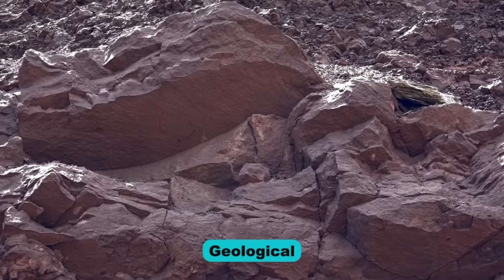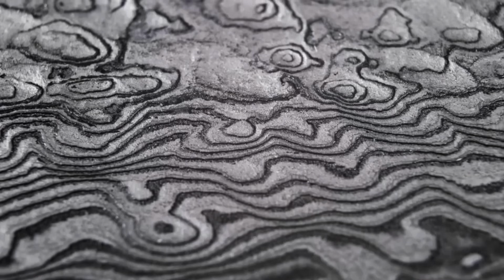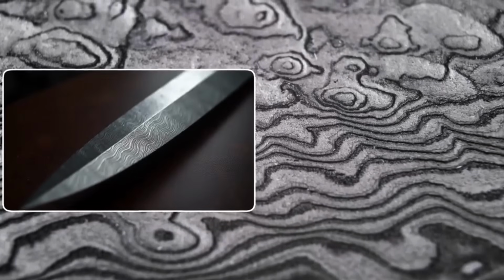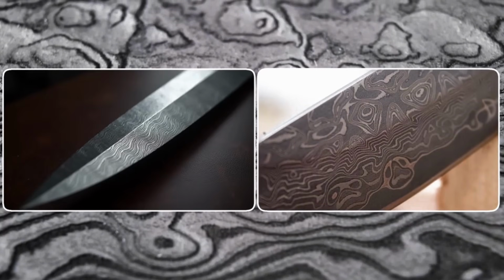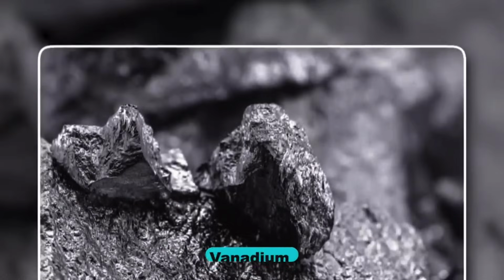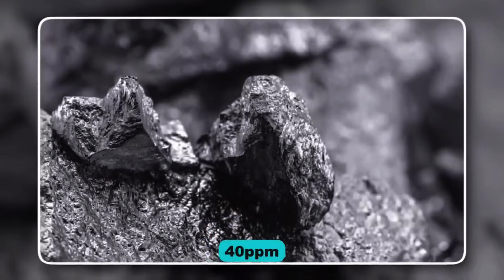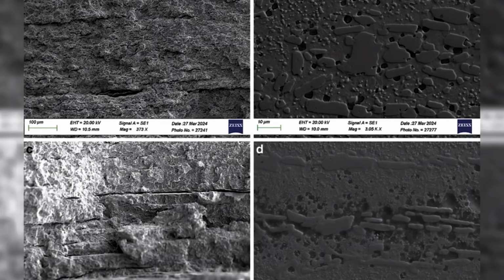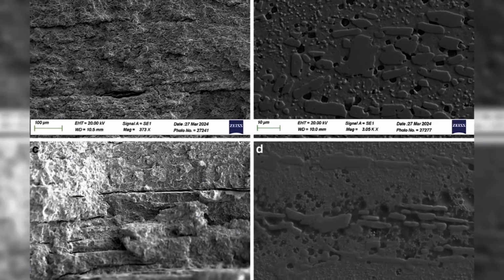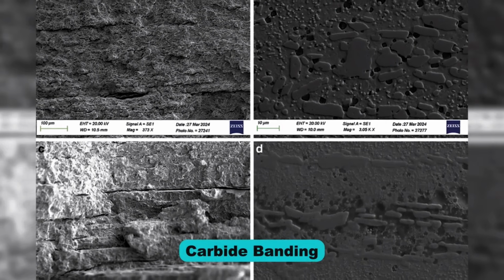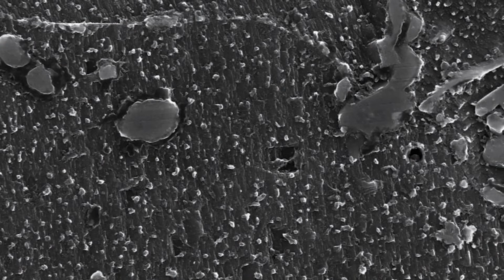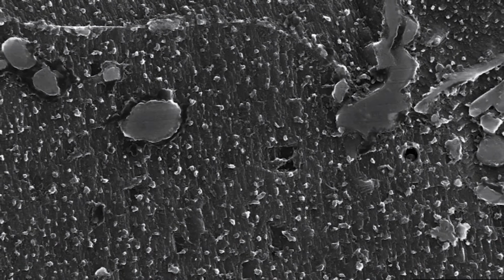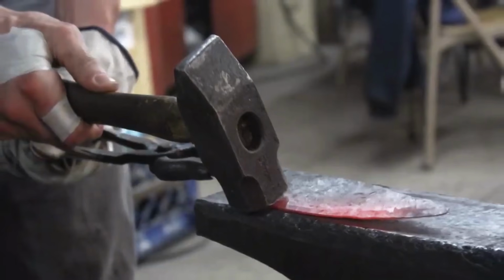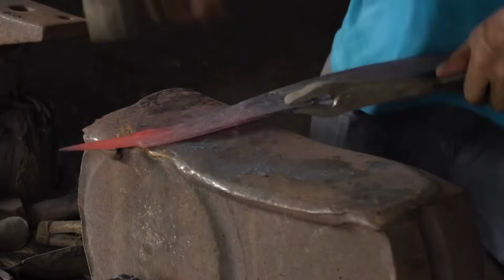The second force was geological. Verhoeven and Pendray's research demonstrated that the famous Damascus pattern depended on trace impurities in the original Indian ore, specifically vanadium at concentrations as low as 40 parts per million. Only certain deposits in certain regions produced steel that could develop the characteristic carbide banding, and when those specific deposits were mined out or became inaccessible through political disruption, the raw material for true Wootz disappeared along with them. Smiths may have continued making crucible steel, but the blades stopped showing the pattern, and without the pattern there was